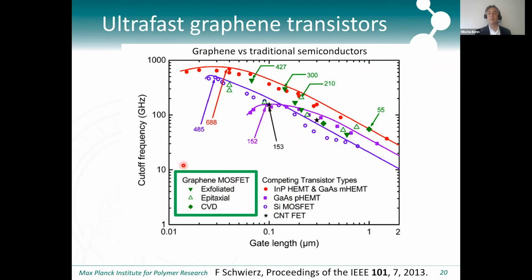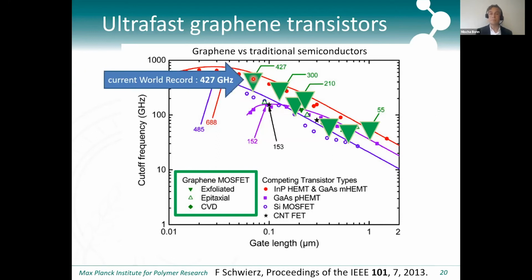But interestingly, if we look at the graphene based transistors, they sort of got stuck at 400 gigahertz. And this was in 2013. So since then, there has not been a faster graphene-based field effect transistor. And so you might think, well, you just showed me that this is such a fantastic material, it's so conductive, only a monolayer, so it should be ideal for making field effect transistors. So is there some intrinsic limitation why you cannot go beyond this 400 gigahertz? And I will show you that indeed there is a problem with graphene that is intrinsic to graphene that we can't really overcome, and that is limiting the device performance, at least in terms of field effect transistors. So this is still the current world record. This was the world record in 2013.